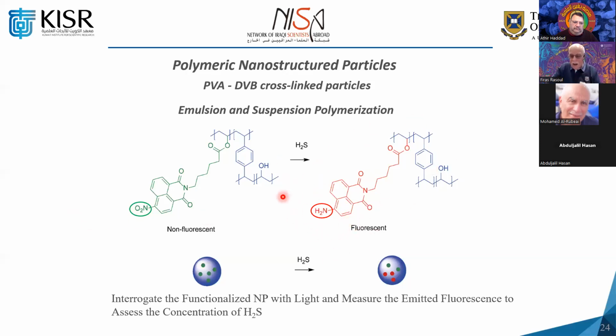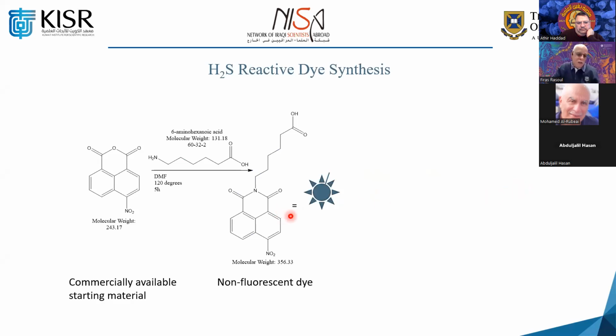The reaction is relatively fast. Within probably a few minutes, you will be able to collect it from the other end, and you will be able to quantify it by looking at fluorescence spectroscopy. So you'll be able to use this technology to interrogate the functionalized nanoparticle with light and measure the emitted fluorescence in order to assess the concentration of H2S. So this is really the approach. So let me start. For the chemists, I think probably the majority of the participants might be chemists, to show you what we did.